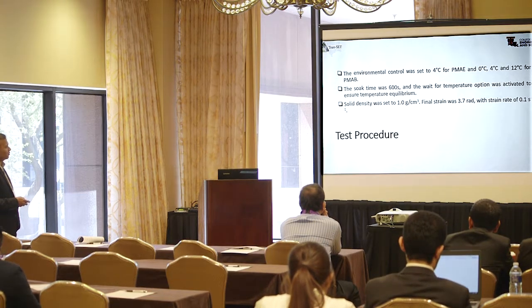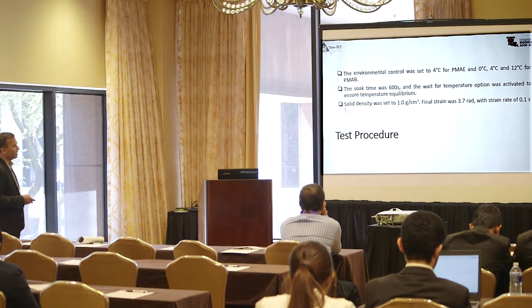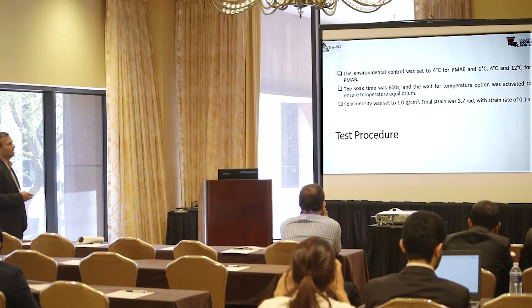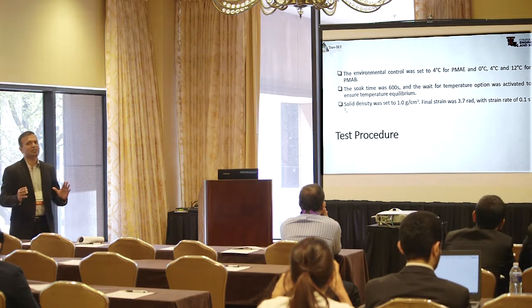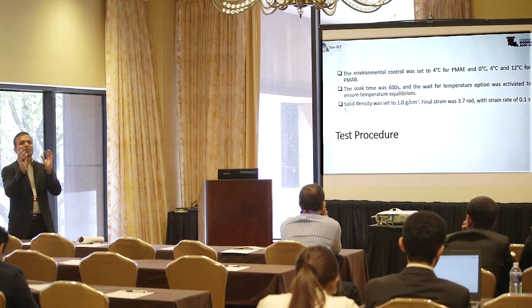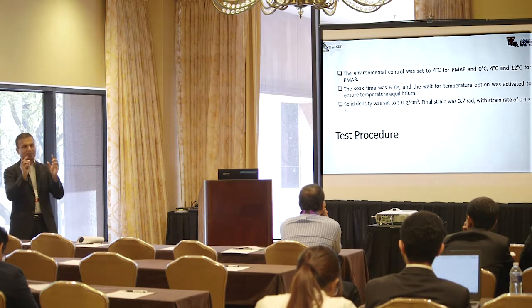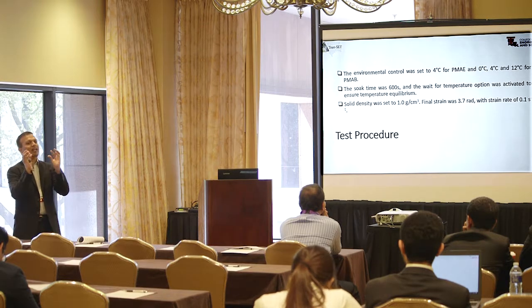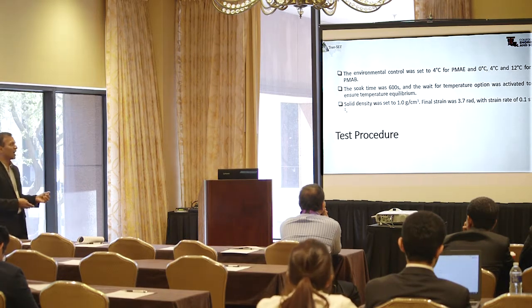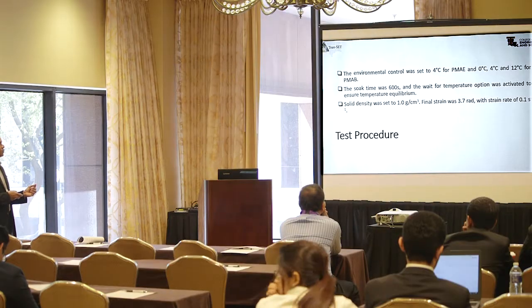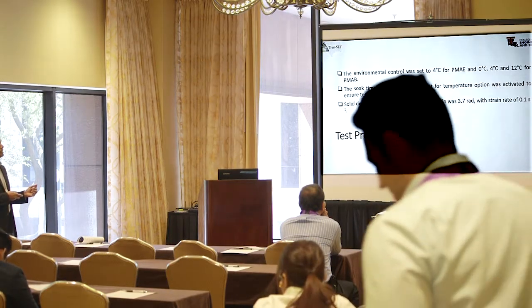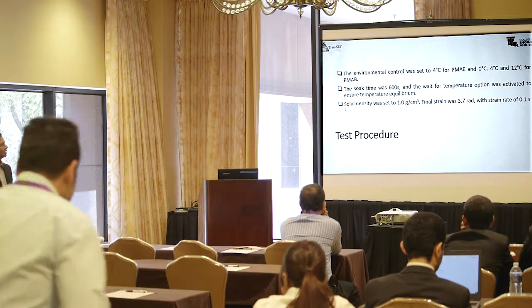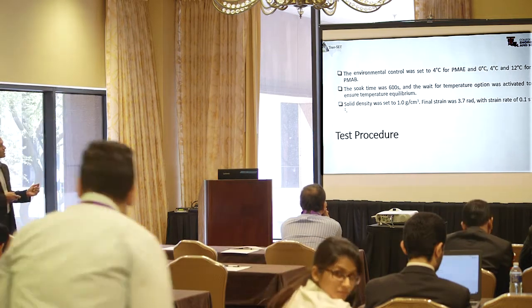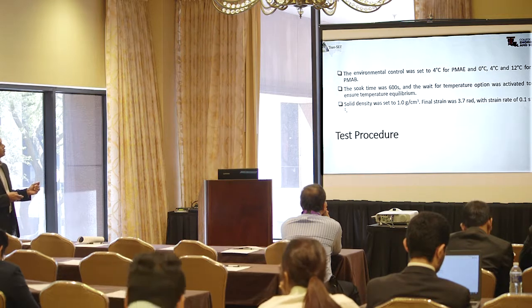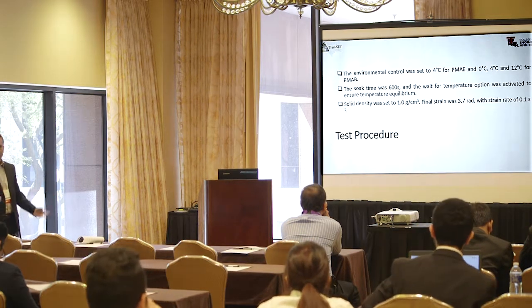Solid density was set to 1.0 gram per cubic centimeter. Final strain was 3.7 radian. As you'll see a little bit later, the two drums rotate, so you cannot actually continue the rotation because they need to overlap. So you have to limit it to within half a rotation or so. Our maximum strain was 3.7 radian. We went at 0.1 radian per second, so that means it took us only 37 seconds to finish the test.